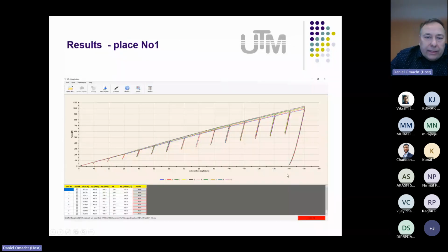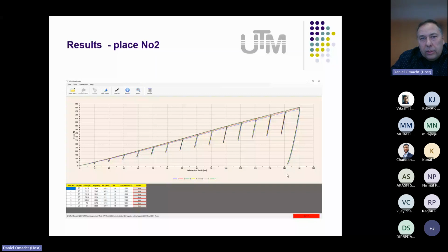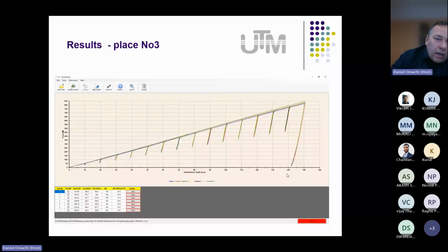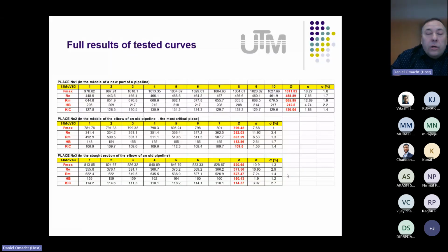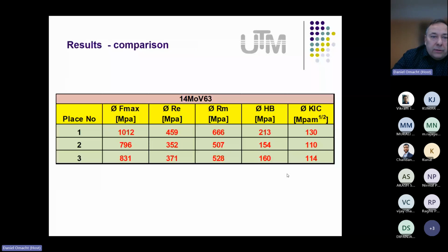Here you can see the testing curves from place number 1, from place number 2, and from the last point. The curves were evaluated by our model because we knew what kind of material it is. So we used the low alloy model for evaluation, and the results are visible here. A summary of the results is in this table.